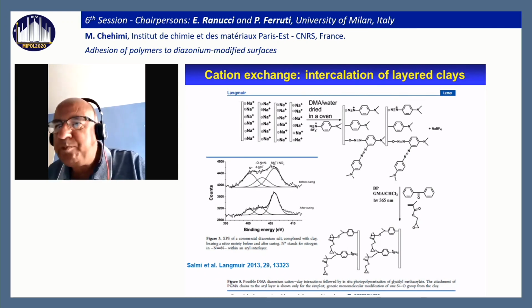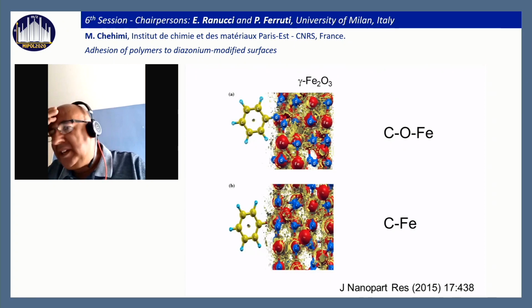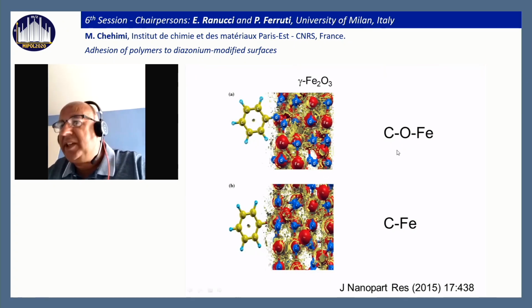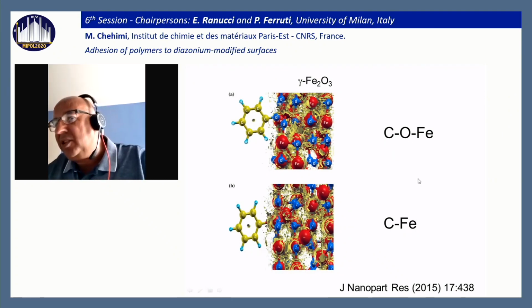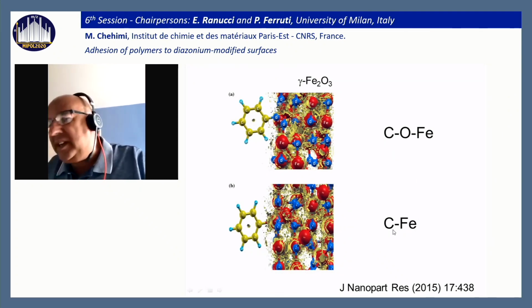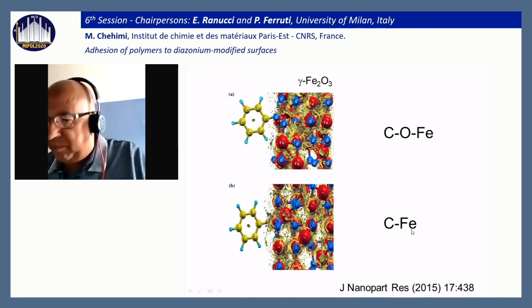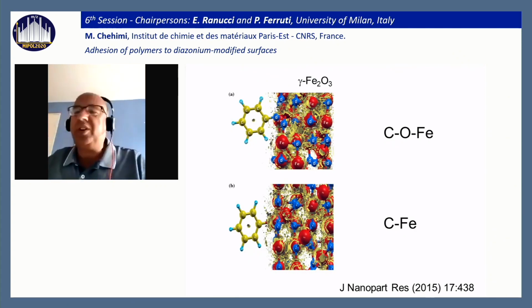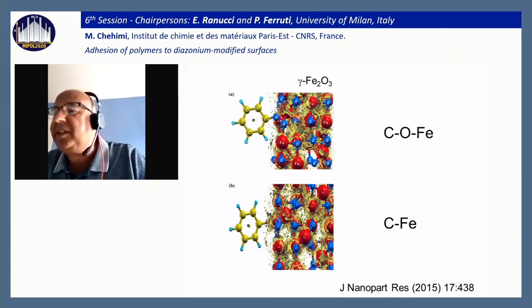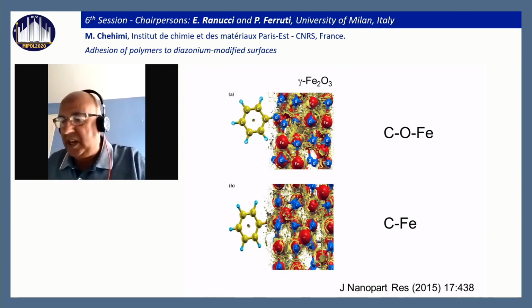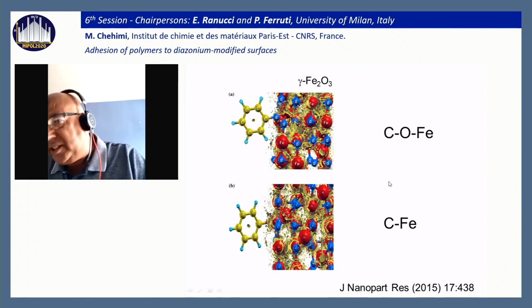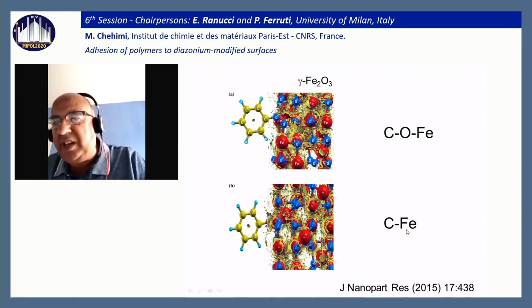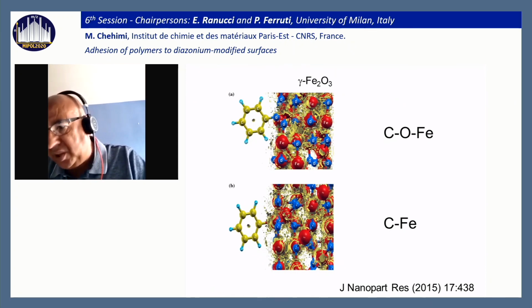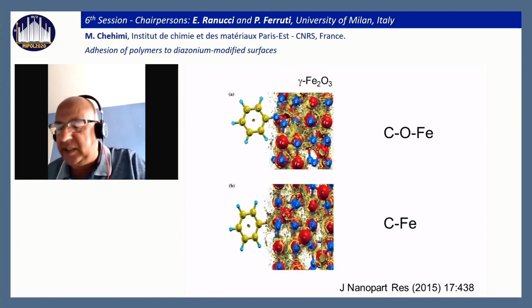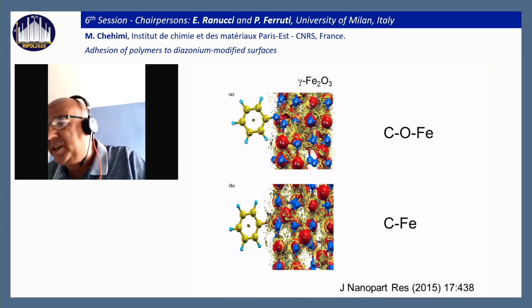So by computational chemistry, it has also been demonstrated that there are interfacial covalent bonds, carbon-oxygen-iron, or directly the carbon-iron bond. And this has given credit to our work by XPS in 2003, when we demonstrated the existence of the carbon-iron bond. It was controversial, and some people didn't believe in the existence of the carbon-iron bond, although we had shown that by XPS.